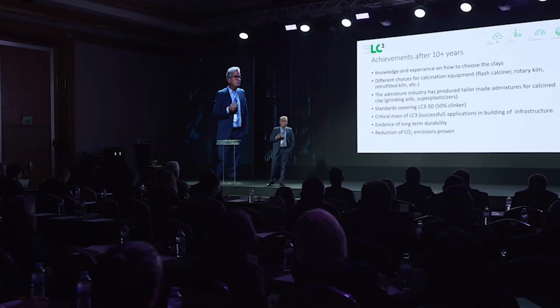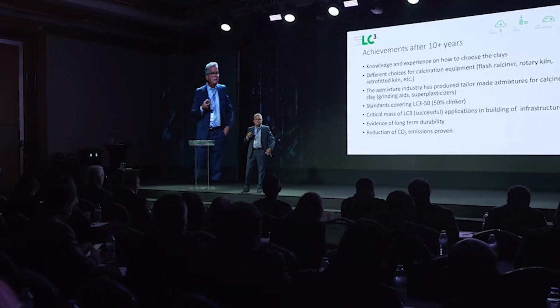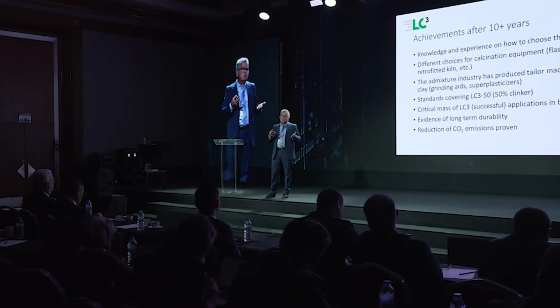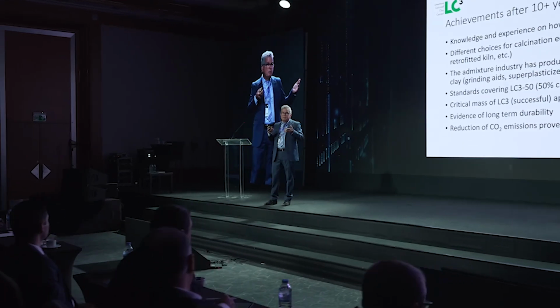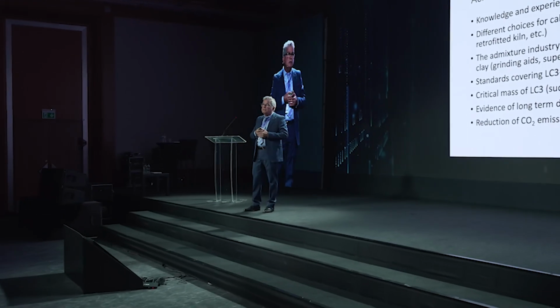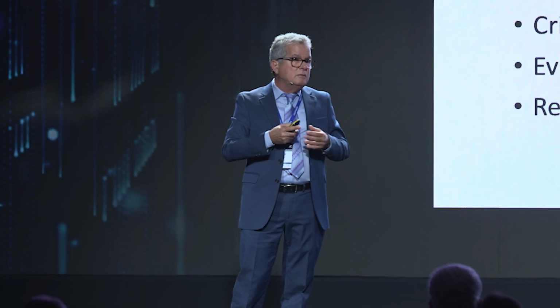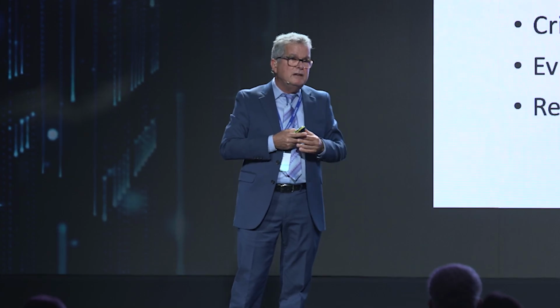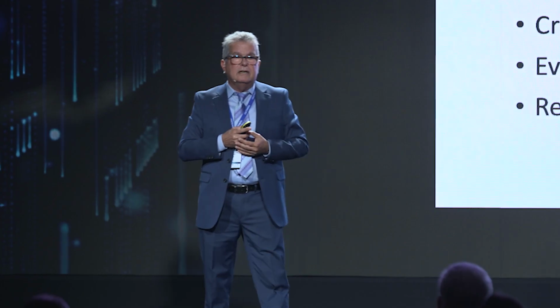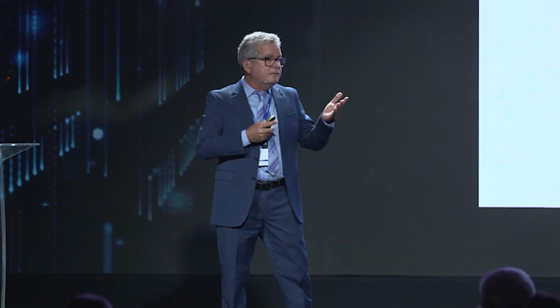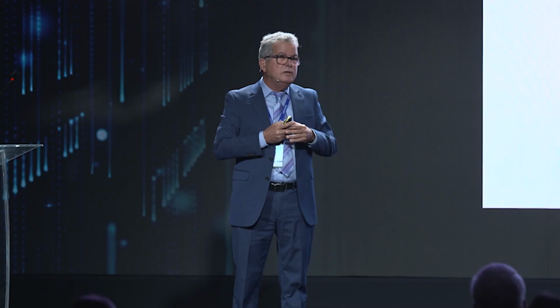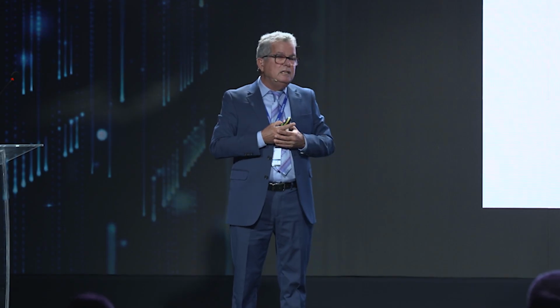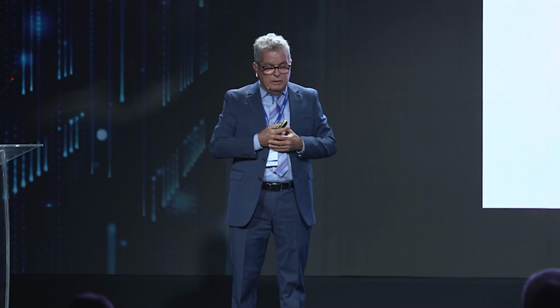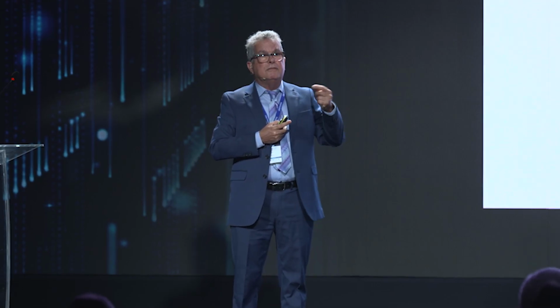Also, standards. Many countries have developed standards adapting. The first and most important one was EN 197 Part 5, which was able to reduce the clinker content to 50%. This is a breakthrough, because before it was 65. But also when you look at the US, the ASTM C595 already has that. In India, Professor Bishnoi was able to get the Indian Standards Committee to approve a standard representing the LC3 with lower content. And even today in Africa, there are countries where 35% clinker in these systems is approved.